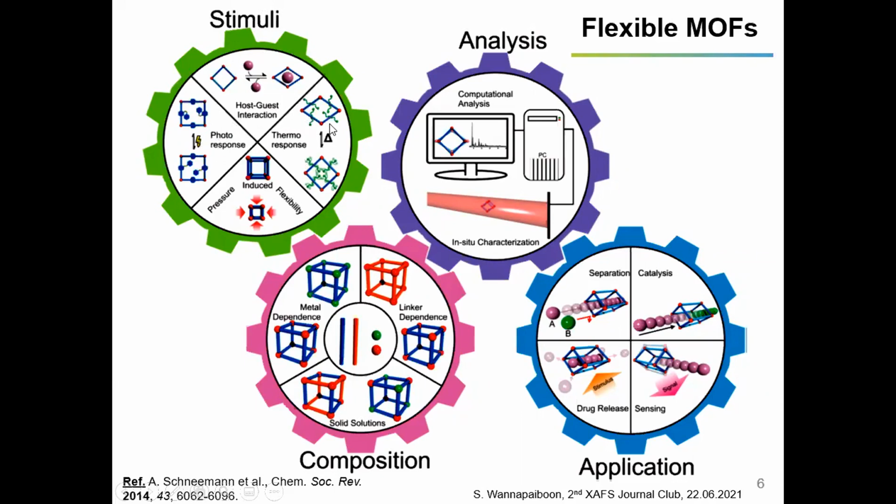So this is also another possibility for using MOF in various kinds of applications. For example, we can use this flexible MOF when we would like to get controlled drug release properties. At some specific external stimulus, we can store the target molecule inside the pore of MOF. Once we apply another stimulus that induces a structural change, for example, from the large pore into the narrow pore, the molecule inside is released. So basically this can be used as a smart material for drug release and drug encapsulation.